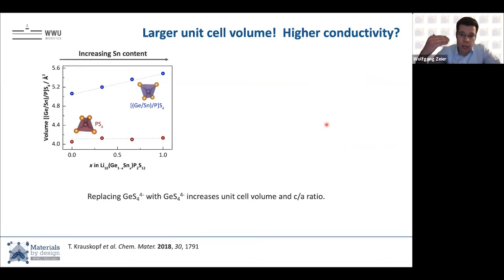And so by doing isoelectronic substitutions of germanium with tin, if we just look at this tetrahedron where germanium and tin are sitting, we see an expansion on that side. So tin is really going on this germanium side. The PS4 side stays the same, so we're not substituting there. So it's just one position in the unit cell where we're changing things.